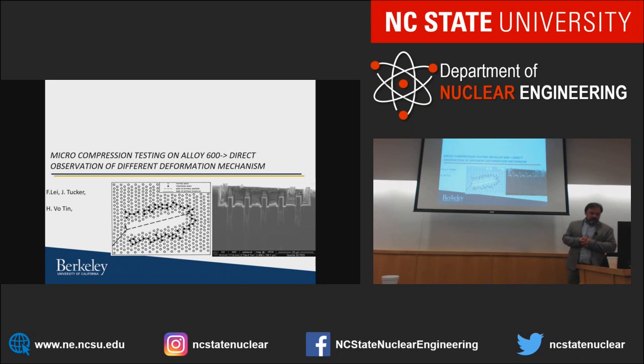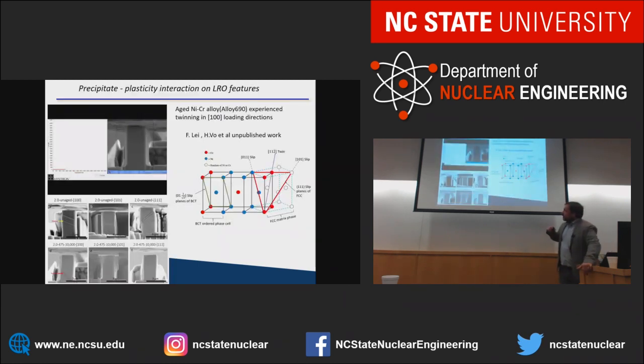Now, another interesting thing you can do with these in situ tests, you can actually learn something about the deformation mode itself. So in this instance, we look at the nickel chromium alloy. That actually hasn't been radiation damaged, but it's interesting because the deformation mode suddenly changes. This material is a heat exchanger material, a model alloy to alloy 690. And there's a fear that these alloys may form long-range ordered features where chromium and nickel have some ordered structure to them. Think of it as an ordered precipitate.